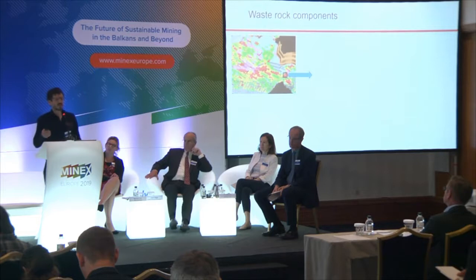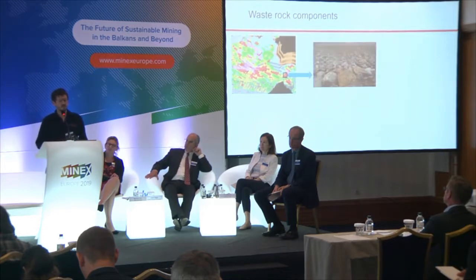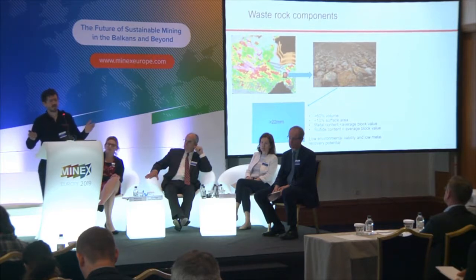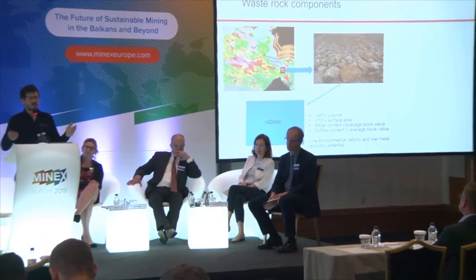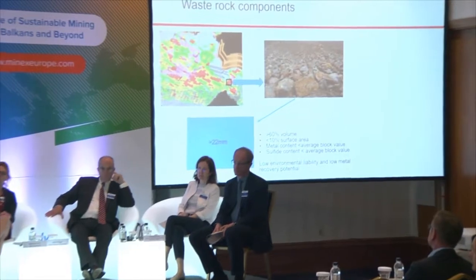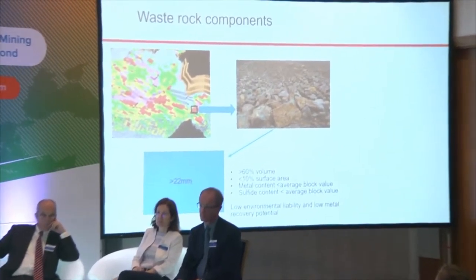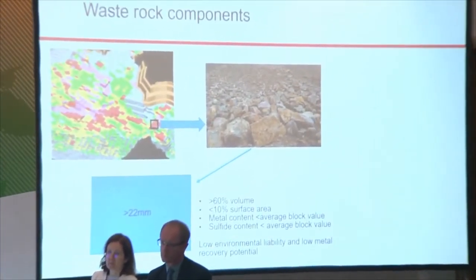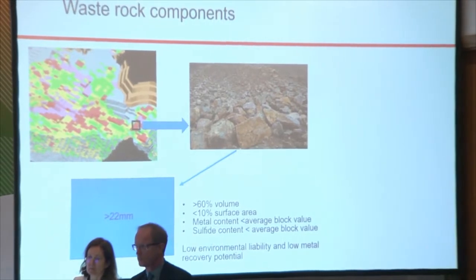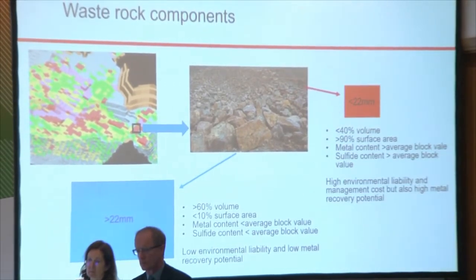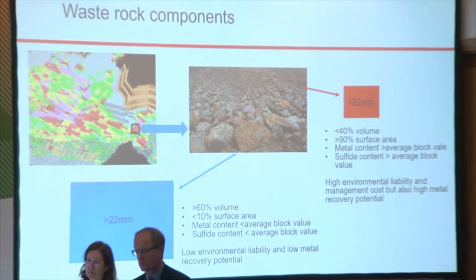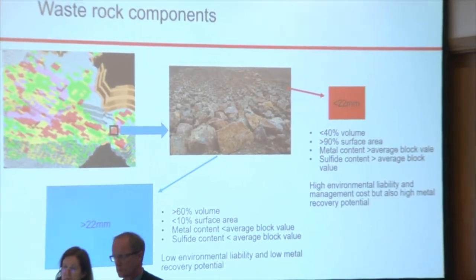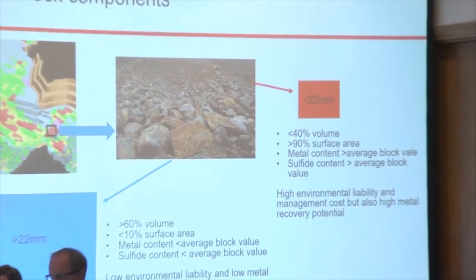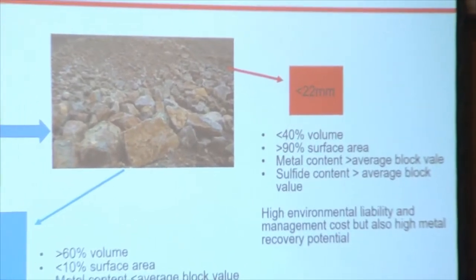So if you look at the components of this, this is the block from the block model. After it's blasted, we get a large volume, 60% or something, of coarse material, less than 10% of the surface area, has a lower metal grade than the average block, has a lower sulfide grade than the average block. It's generally got a low environmental liability. The fine fraction, which is less than 40% of the volume, has got more than 90% of the surface area, it's got higher metal grade, has got a higher sulfide grade.